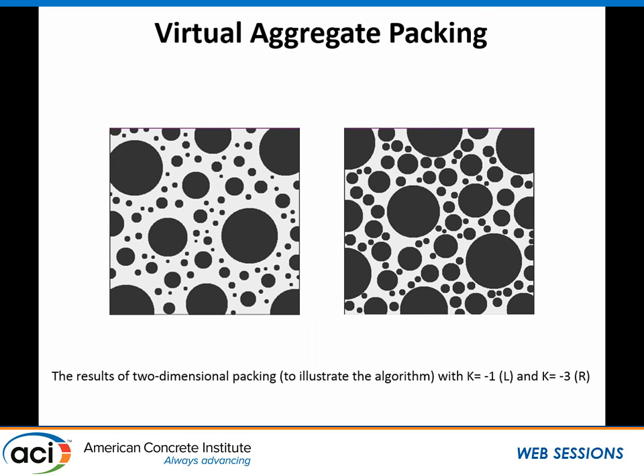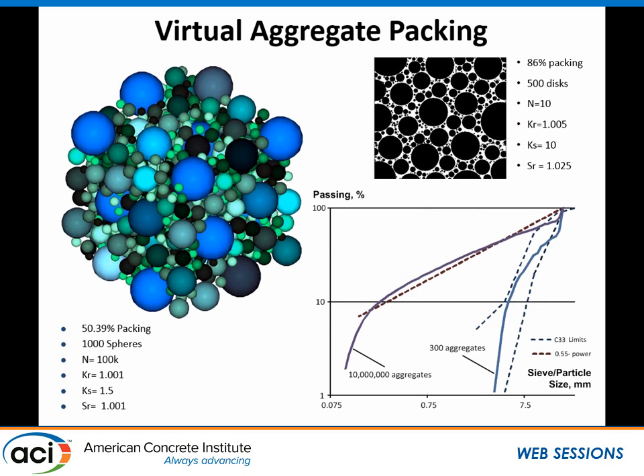Briefly talking about virtual packing, this is a tool. Right now we've talked about discrete models and experiments, but here it's a real-world distribution of particles. It's assumed that all the particles are spheres, and it can be run in 2D or 3D, with a limited number of particles for 2D, and unlimited, well, you can go up to 100 million particles for 3D. What it does is ask you at what rate you want to reduce the diameter of your particles, at what rate you want to reduce the spacing within your particles, and what you want your initial spacing to be set at.